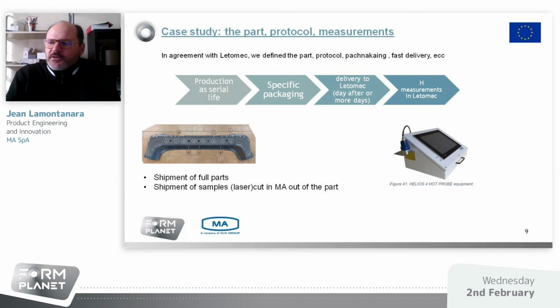Okay, so we apply a special packaging and we deliver to Letomec. Some samples were received the day after the production, so the day after the hot forming, and some other samples arrived in Letomec a few days later, so around 5 to 6 days. Okay, so the samples arrive in Letomec for the measurement using the Helios hot probe equipment, as well described by Linda Bacchi.